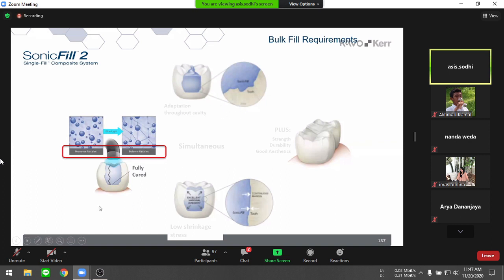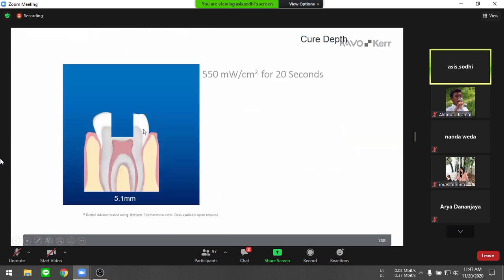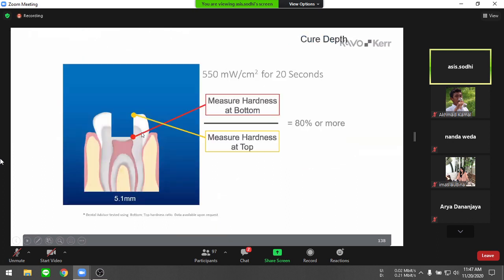Right. The second concern we had is about the curing depth. Now, as per the industry standards, when you cure a material and measure the hardness at the bottom and the hardness at the top and take a ratio of these hardnesses, if it is 80% or more, it is considered to be clinically acceptable. With Sonic Fill, we are able to achieve 97% of this ratio, which means that we don't have to worry about the thickness of the 5 mm, and we are able to achieve ideal curing at the bottom of the cavity also.